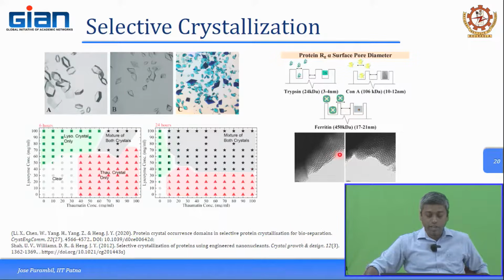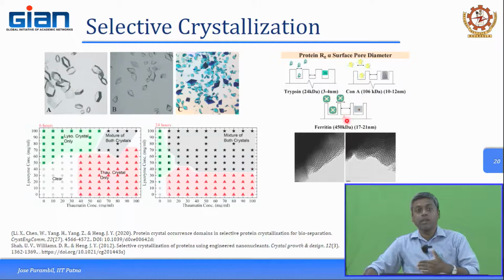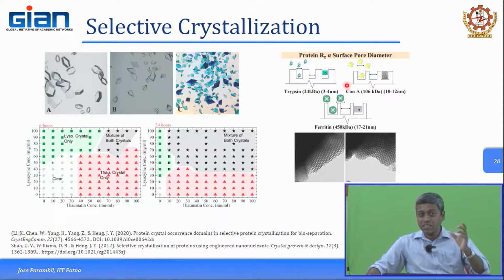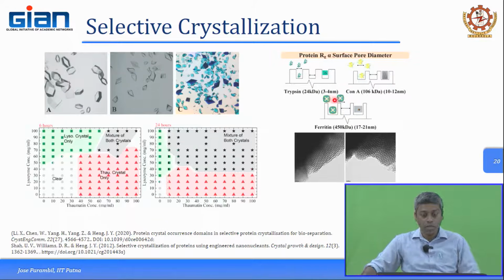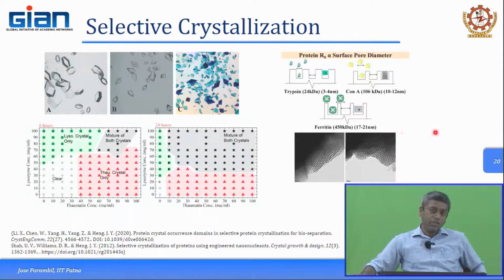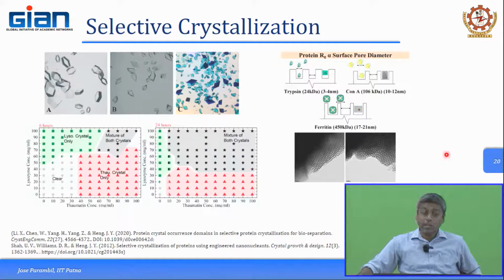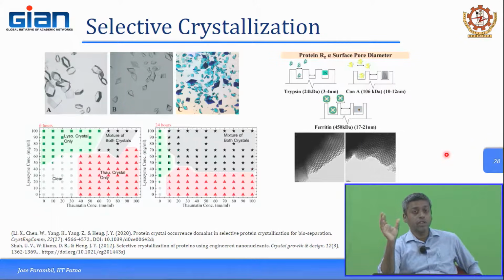So, in this case what they have used is porous silica particles, or porous silica with specific nanometer range pores, and some of the proteins crystallize at one particular pore size, and other proteins crystallize in the presence of other particular pore sizes. So, these sort of pores or heterogeneous templates can be used in order to enhance nucleation of one over the other. So, trypsin, for example, nucleates if you have pores in the range of 3 to 4, whereas ferritin, being a larger protein, nucleates at a larger one. So, these are again correlated back to the radius of gyration of the actual protein molecule.